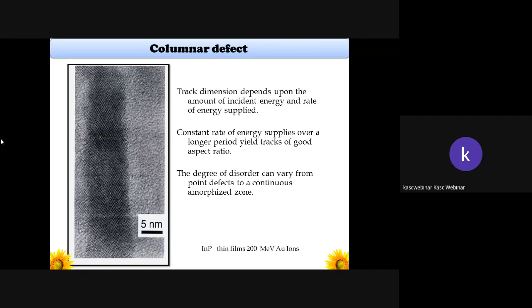Actually, the track dimension depends on the amount of instant energy and the rate of energy deposited, nothing but the ion fluence. Then the constant rate of energy supplied over a longer period of time yields a track of good aspect ratio, or length to width ratio. The degree of disorder can vary from very point defects to a continuous amorphous zone.